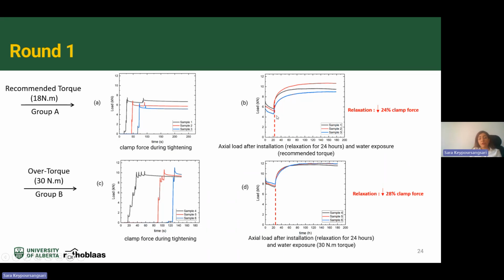After that, we poured water inside the bucket in order to see the effect of the moisture content change on axial load, which was measured by the load cells. You can see that in the relaxation phase, there was around a 24% clamp force decrease. We did the same thing for group B. We increased the torque to 30 Newton meter and waited for 24 hours, and after that, we increased the moisture content. For group B, the relaxation was about 28%, which means that 28% of this clamp force decreased over the relaxation phase.